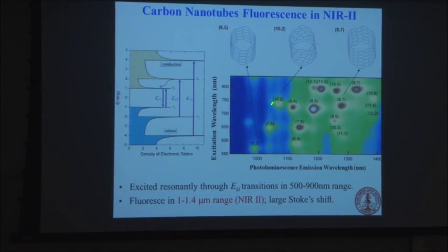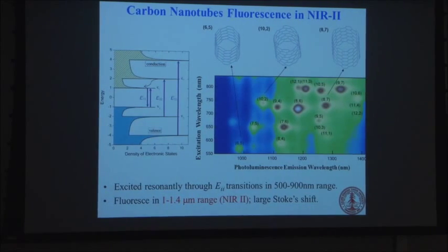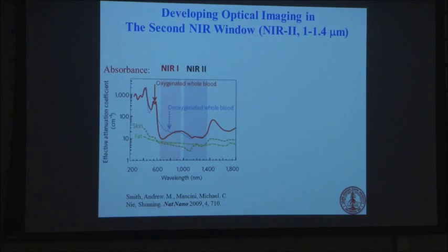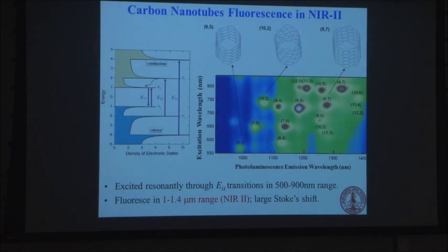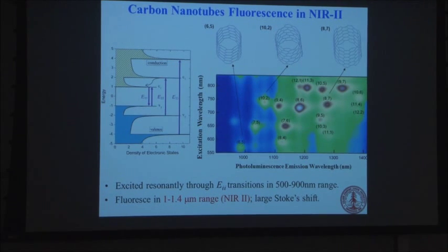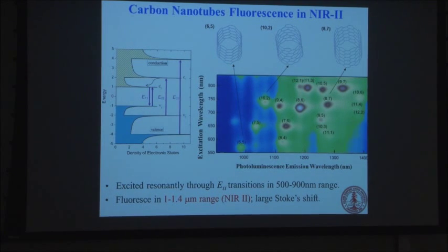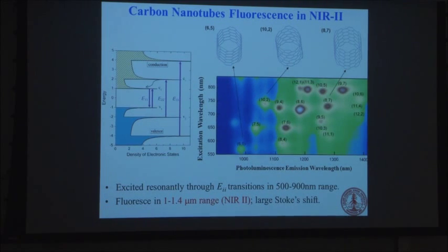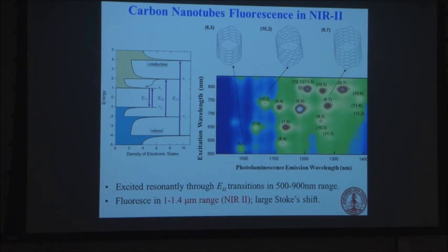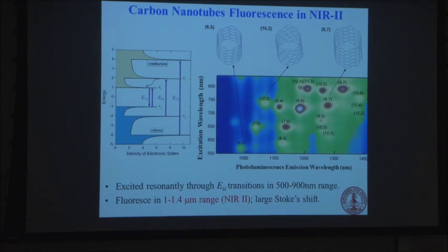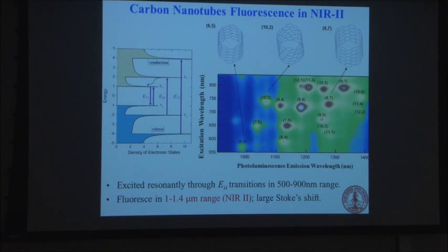So you can actually get absorption in the visible, or something like 800 nanometers, and then they emit light almost in the IR. They emit from 1 micron to 1.4 micron, and we call this region the near IR2 window, because traditionally near IR is about 800 nanometers. This is still near IR, but it's in a slightly different window.